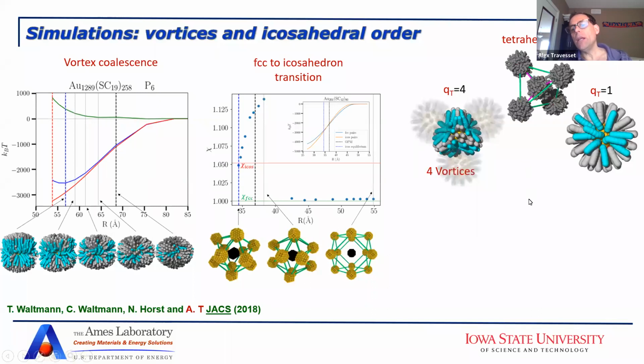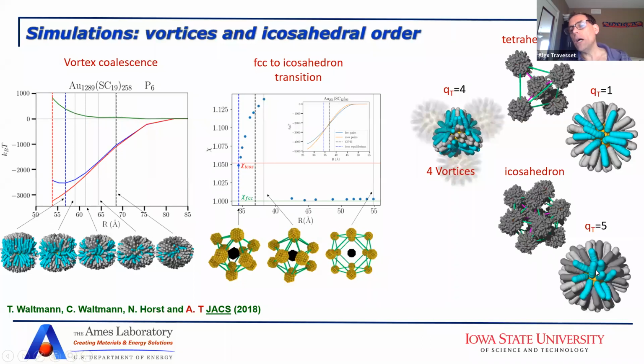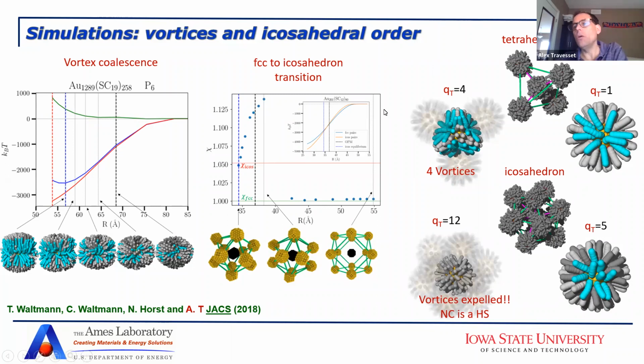What happens if you do the same thing now with an icosahedron? Well, in that case, you have a coordination 12. And you have that the particles outside, they do have vortices, but the particle in the center doesn't have any vortices. The vortices are expelled. So some of these are a little bit tilted, but they are all straight. And therefore, what we show is that the particle at the center, in this particular case, is behaving as it should, as a hard sphere. So what we see is that with these all atom molecular dynamic simulations, we are able to show that indeed these particles behave as hard spheres when they do, and they behave as with vortices when they should.